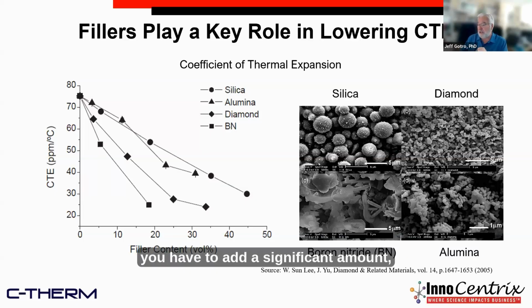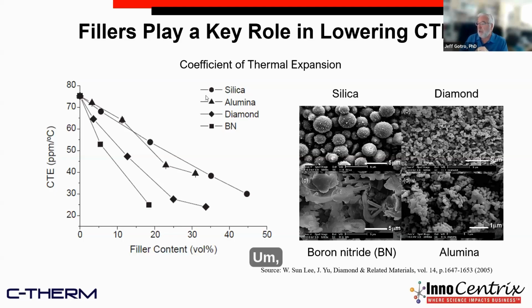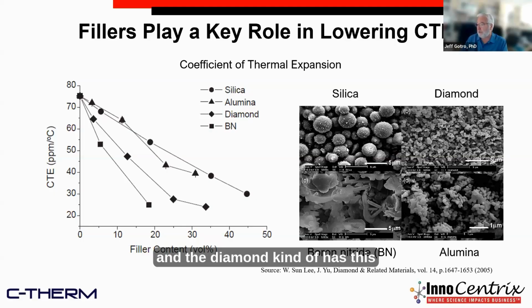But you have to add a significant amount, a high volume percent, of silica. Alumina is a little better. Diamond gets you there much faster. And boron nitride gets you the lower CTE. But boron nitride, though, is platy. So it has this plate-like morphology, where silica, we saw earlier, is spherical. And the diamond kind of has this spherical type of shape, but they're very small. And then alumina is kind of in the middle, right? But the point is you use these fillers to control the thermal expansion.